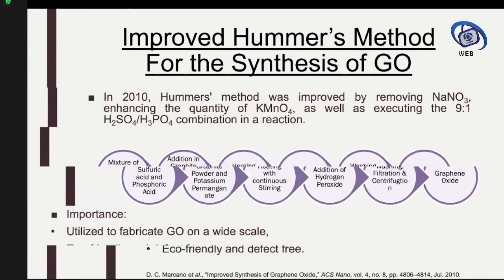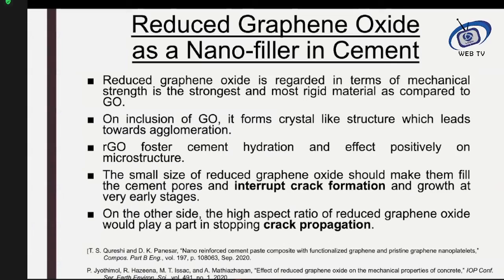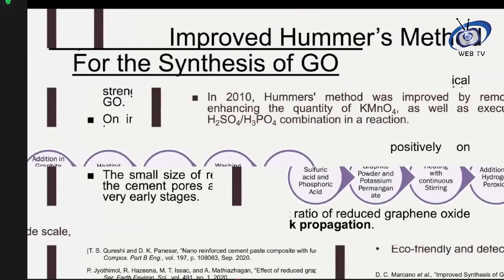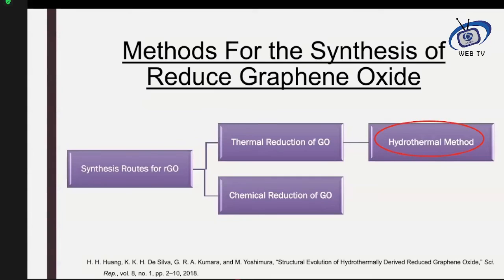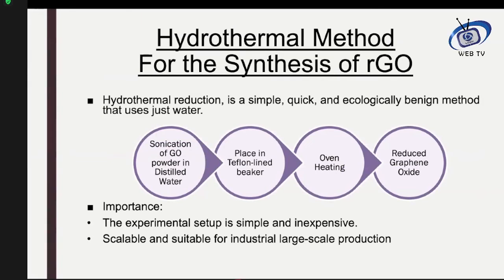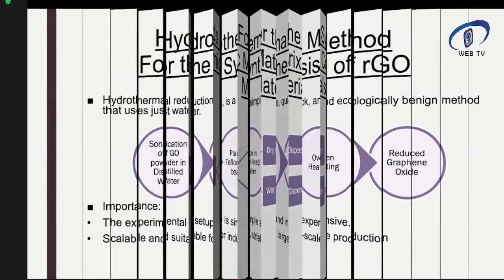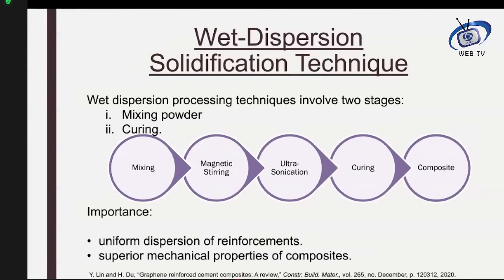So we will move toward the fabrication of graphene and reduced graphene. The synthesis of the reduced graphene was with the help of the hydrothermal method. In this work, the hydrothermal method was used for the synthesis of reduced graphene oxide. The different steps used are represented in the schematic diagram. Then that reduced graphene oxide was used as a reinforcement for cement.